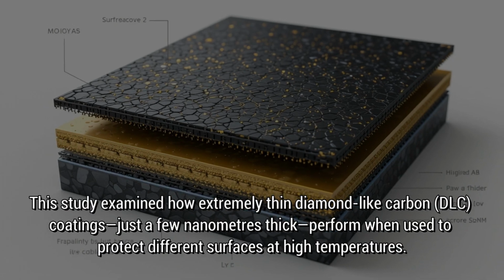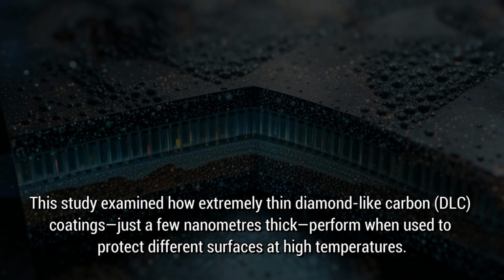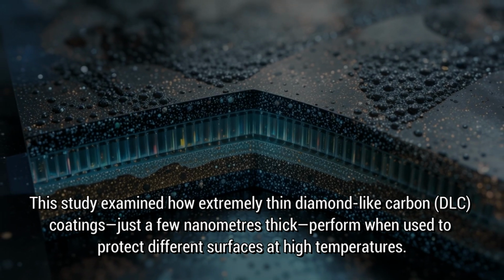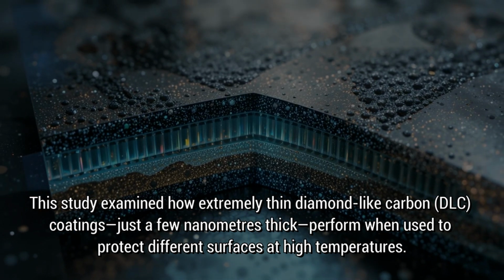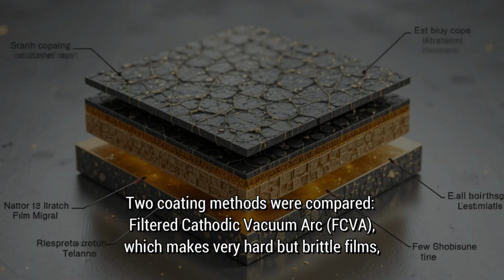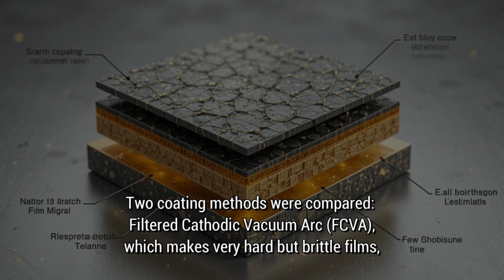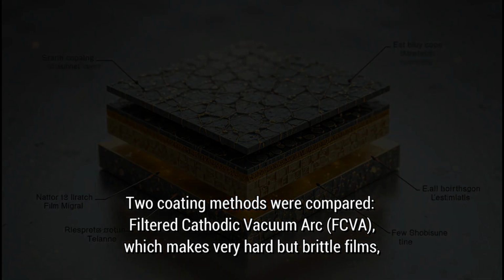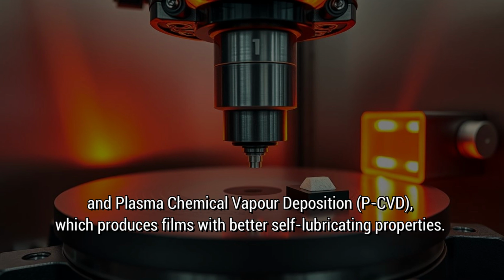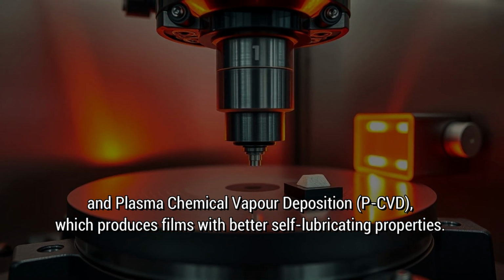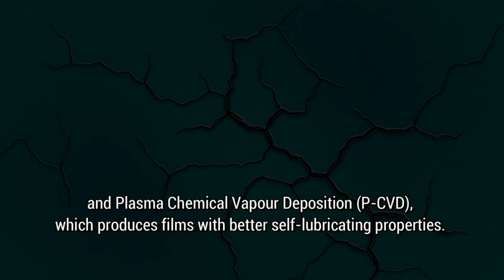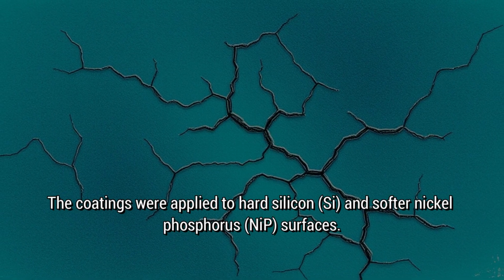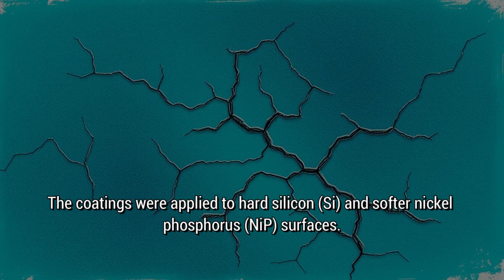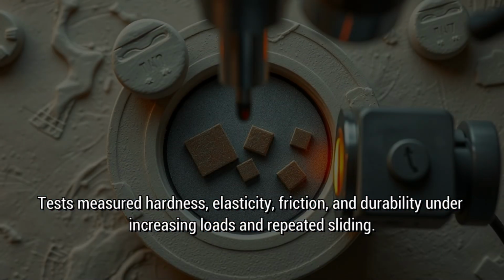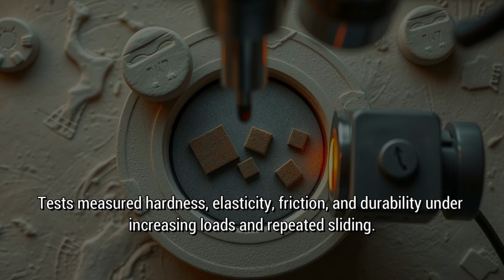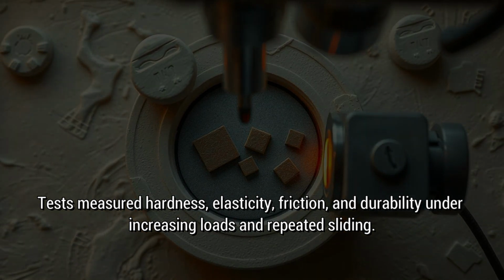Conclusions. This study examined how extremely thin diamond-like carbon, DLC, coatings, just a few nanometers thick, perform when used to protect different surfaces at high temperatures. Two coating methods were compared: filtered cathodic vacuum arc, FCVA, which makes very hard but brittle films, and plasma chemical vapor deposition, P-CVD, which produces films with better self-lubricating properties. The coatings were applied to hard silicon, Si, and softer nickel phosphorus, NiP, surfaces. Tests measured hardness, elasticity, friction, and durability under increasing loads and repeated sliding.